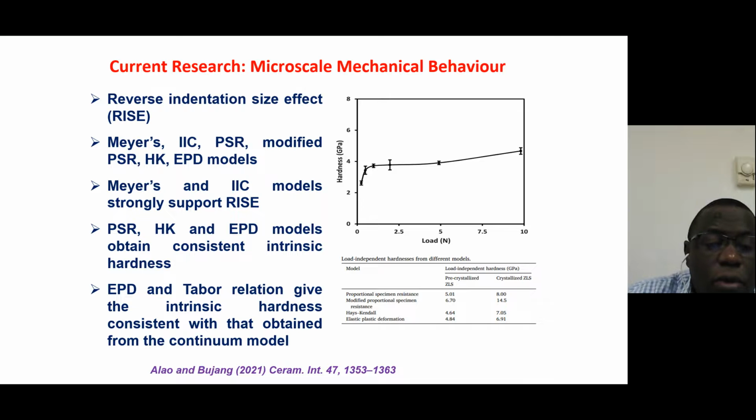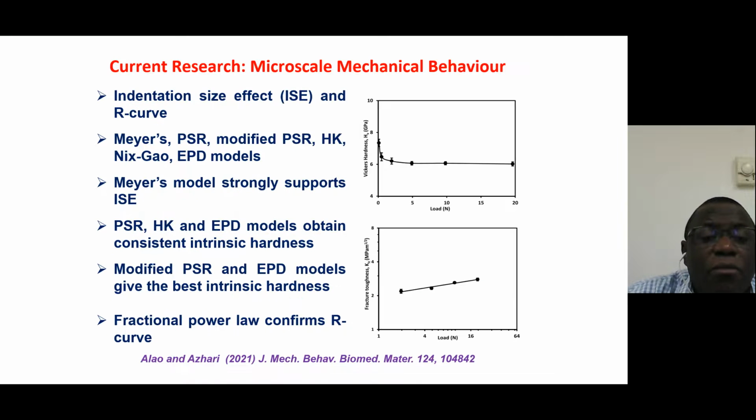Moving on, I also did the same for lithium disilicate glass ceramics. I investigated the Vickers response of lithium disilicate glass ceramics to different loads. And I obtained that the response was normal indentation size effect. I also applied the same methodology to find the intrinsic Vickers hardness for the two materials.